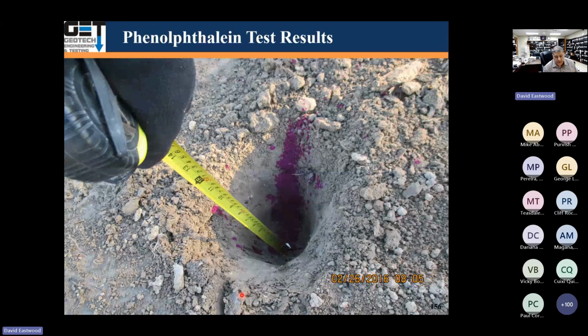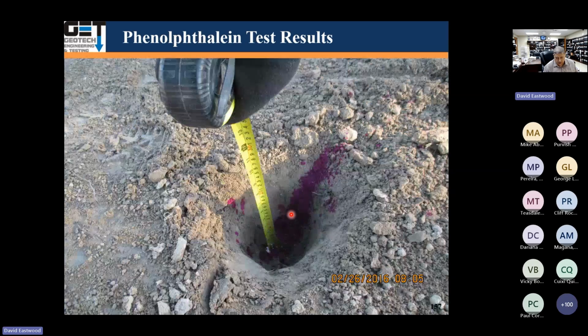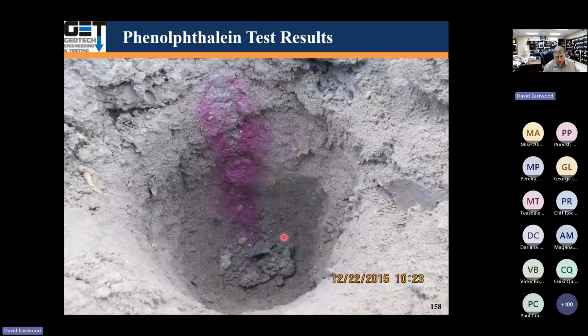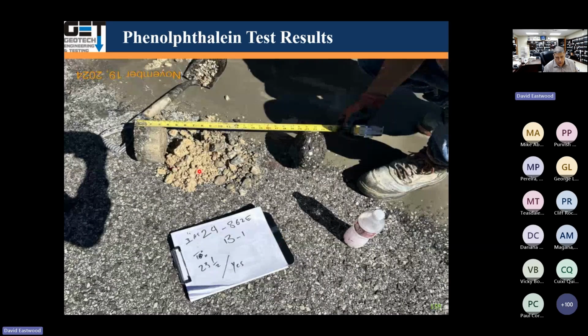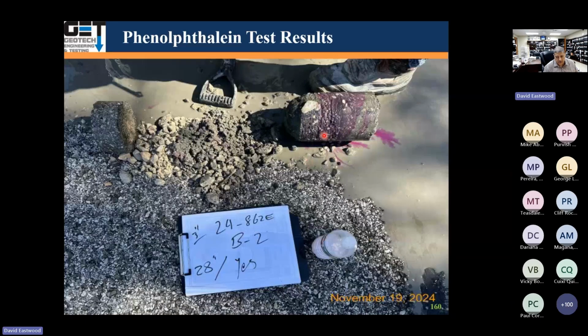Phenolphthalein testing. If your stabilized layer has cement or lime in it, you can put these chemicals on it, and it will turn purple. It's called phenolphthalein. So when we core this stuff, we look at the asphalt, the base, and this is the stabilized layer. Here is no phenolphthalein because it didn't turn purple. Here, the base stabilized layer turned purple. There's phenolphthalein in it.